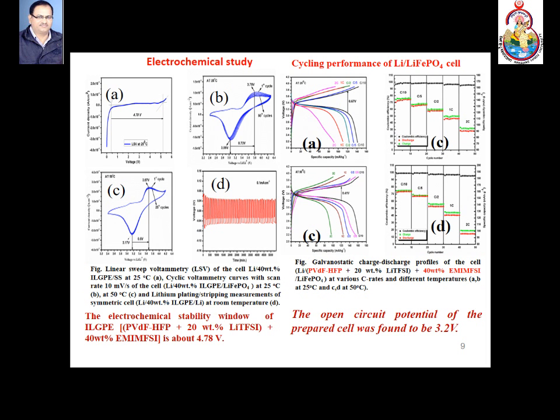Here are some of the results of the lithium cells fabricated using optimized electrolytes based on PVDF-HFP and salt LiTFSI. It can be seen that the electrochemical window is around 4.78 volt, which is wide. The CV indicates that the oxidation reduction potentials indicate the intercalation and deintercalation of ions. For optimized electrolyte and LFP cathode, the discharge capacity obtained is more than 140 milliampere hour per gram. Also, the high rate discharge capacity is high.